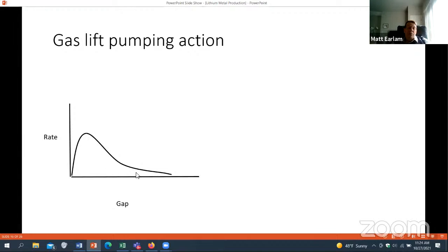And then as you get the gap too far, your pump becomes ineffective because you're not getting a lot of movement of electrolyte compared to the amount of electrolyte that's in there. So there's an optimum gap in terms of pump rate that's somewhere in between 1 and 3 inches in this scenario.